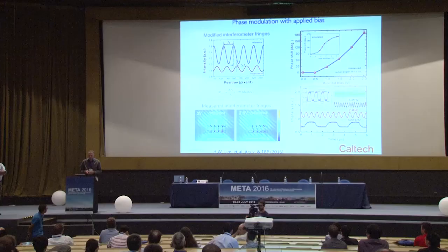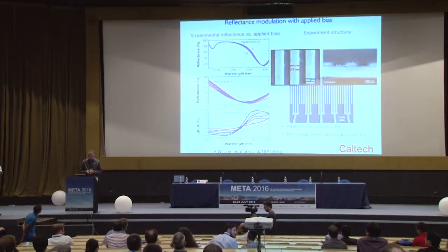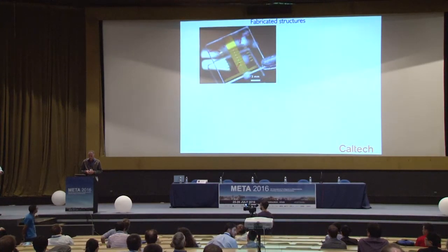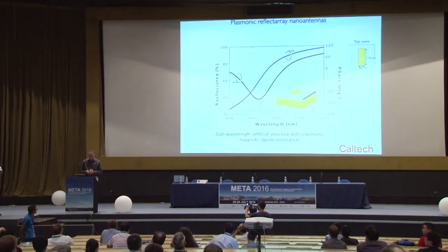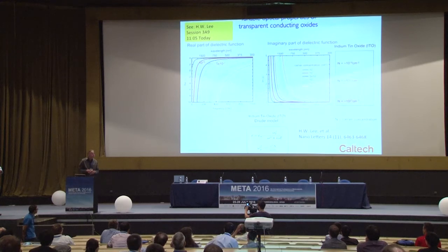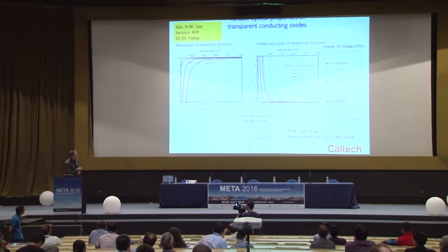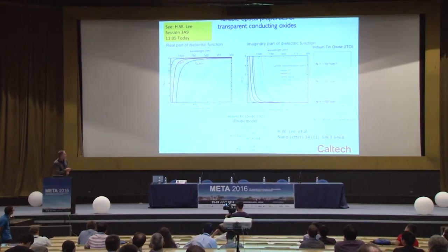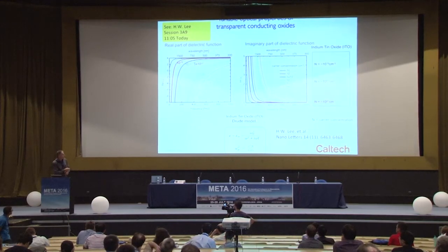Yeah, okay, so that's a very interesting question. So the question was, as you change the real part of the permittivity, how much does the imaginary part change? So you can see that almost directly. ITO is actually a fairly good Drude metal. So you can see here, as we change the real part of the permittivity, we are in fact changing the imaginary part as well. So indeed, you can see that is evidenced by the color change. So there is some loss.